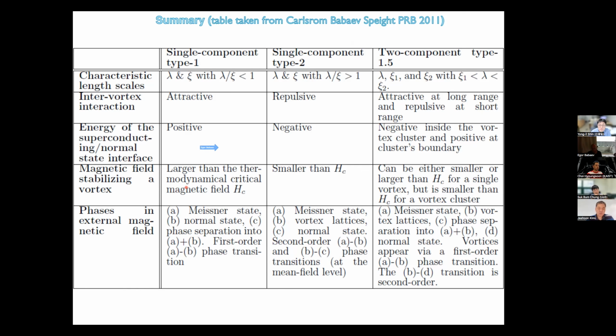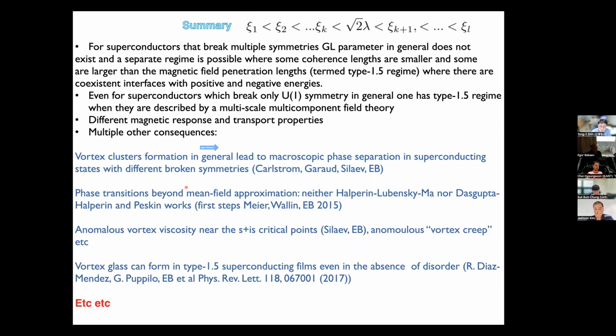So in type 1.5 superconductors, there is a different hierarchy of the fundamental length scales, and in general superconductors break more than one symmetry. There's more than one fundamental length scale, and there are new hierarchies leading to long-range attractive, short-range repulsive interactions. And then there is a macroscopic phase separation, and many other consequences that I list on this conclusion slide. But basically, when we start digging into this hierarchy of length scales, there are many other effects, and one of them is vortex glass formation in a clean system.